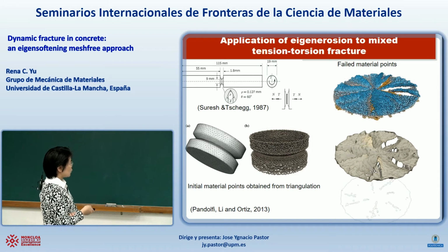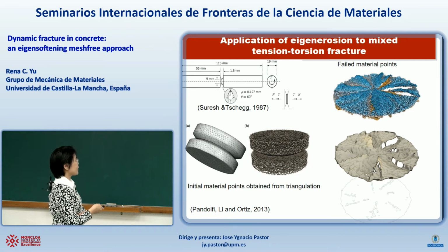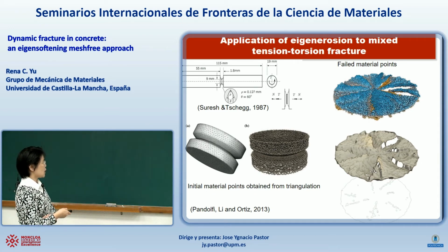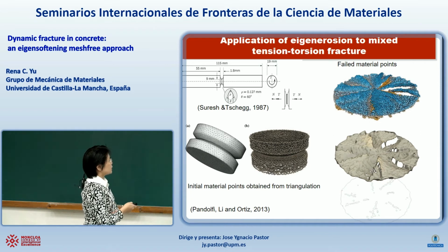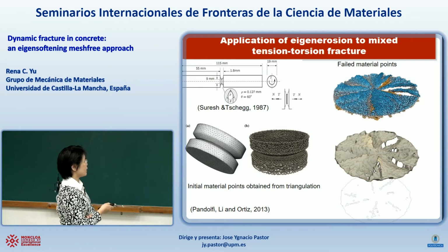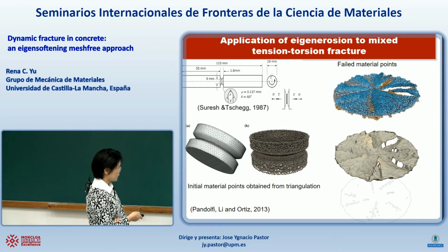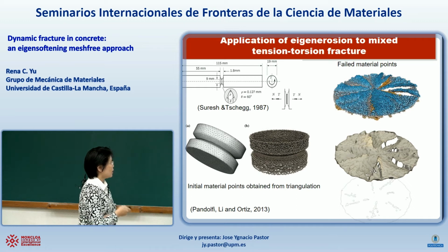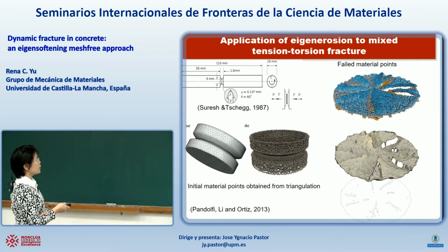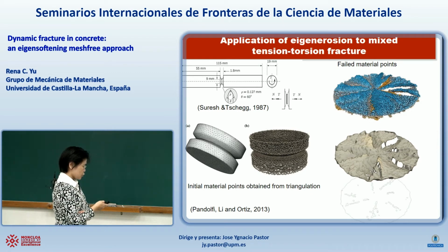So in the work of Pandolfi and Ortiz, they choose only the central part as the notch and do a triangulation of this part, and then take off the mesh. This is what is left with the initial material points, and these are the failed material points. Of course, this is quite a heavy calculation, and this is the reconstructed failure surface. So you see, this is the projected profile. There are some empty areas. This is the mixed tension torsion approach.